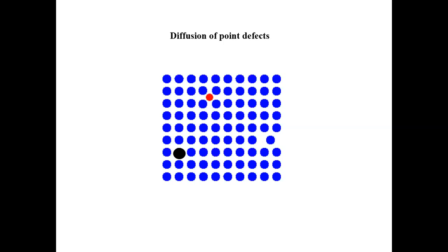Does this picture make sense? So if you look at these two atoms, you start the vacancy from here. Right, and then you see this guy first move, and then the vacancy moves on. But if you focus on this guy, it only does one hop for all this time, right? Well, the vacancy did a lot of hops to go from the original position to all of these positions. So this guy is going to move at a much slower rate. Compared to the vacancy, it does move once, and then it's going to stay there. And for the simulation, it's going to stay there forever. Does this make sense to you?